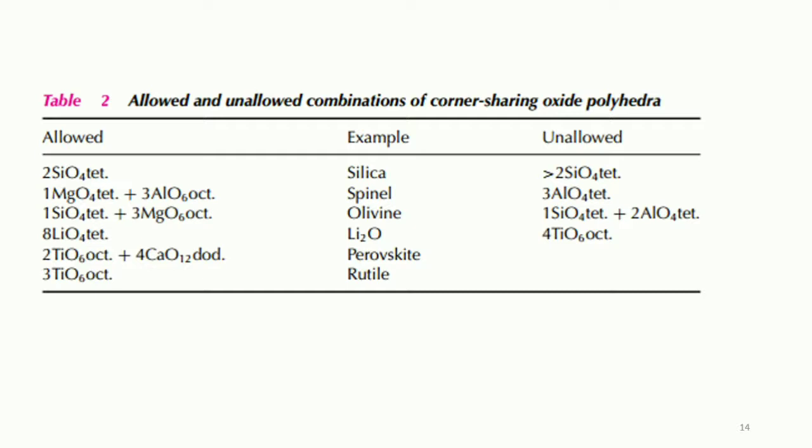Pauling's first rule states that a coordinated polyhedra of anions is formed about each cation. The cation anion distance is determined by the radius sum and coordination number of the cation by radius ratio. The idea that cation anion distances are determined by a radius sum is implicit to every tabulation of ionic radii, since a major objective of such tabulations is to be able to predict correctly interatomic distances. Let us consider some of the coordination number and radius ratio rules.